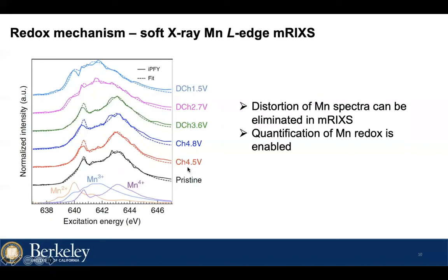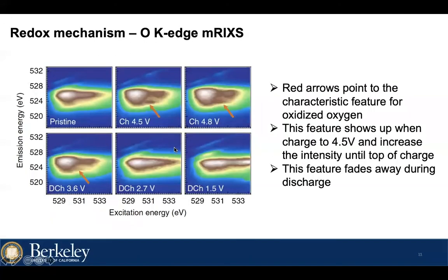of another main and reversible contribution to the capacity, from oxygen redox. And here is the oxygen K-edge mRIXS, which is an advanced technique to characterize the oxidized oxygen. This technique is more precise and is more direct evidence of the oxidized oxygen in the lattice if you compare it to typical soft XAS spectra. And this 2D mapping of the oxygen K edge gives the intensity by color. Blue means low intensity and brown-white means high intensity.